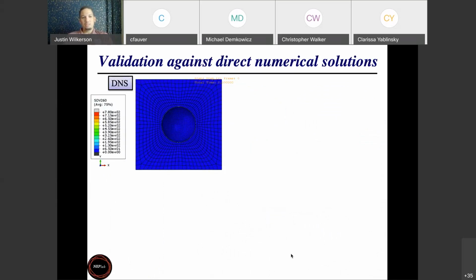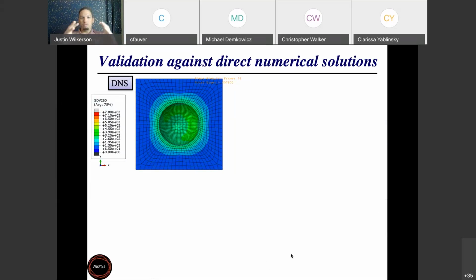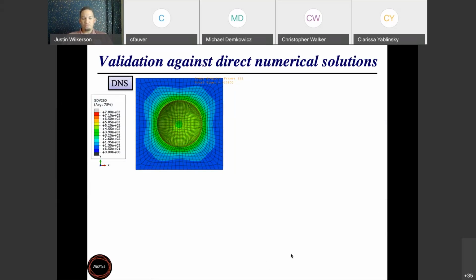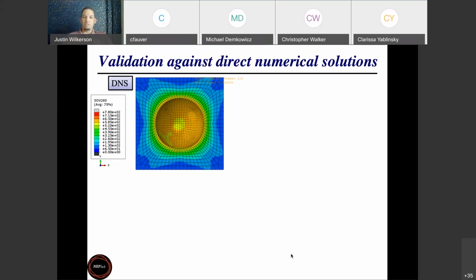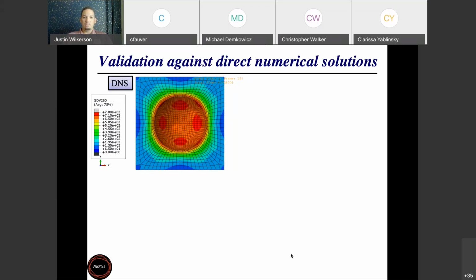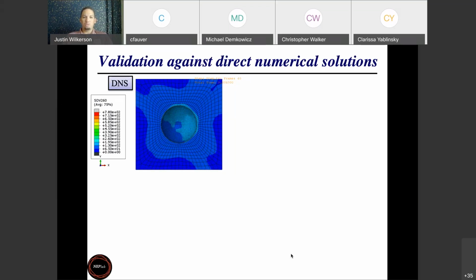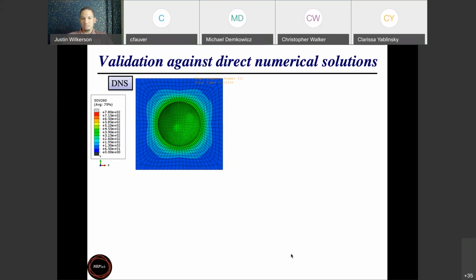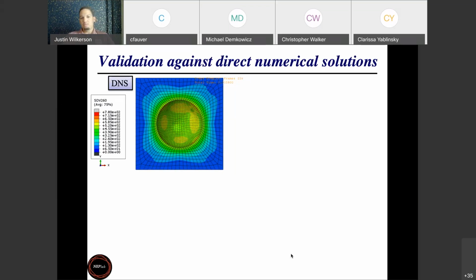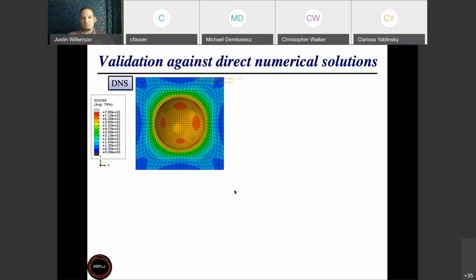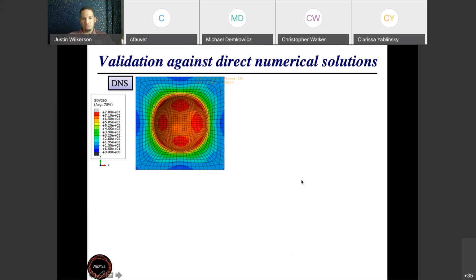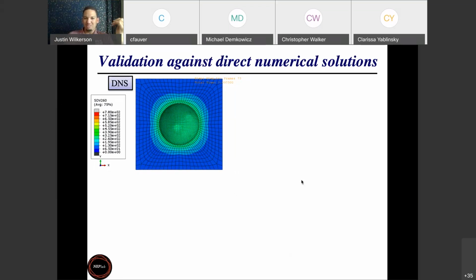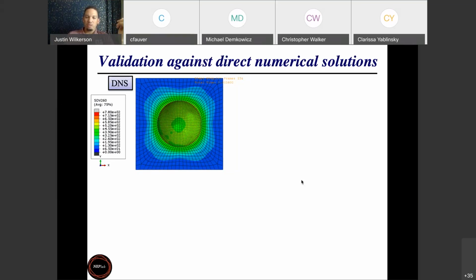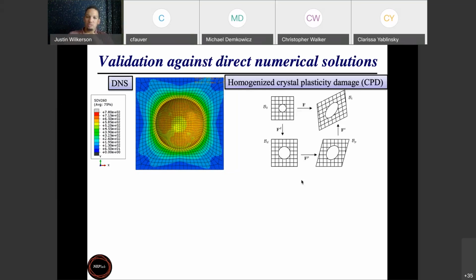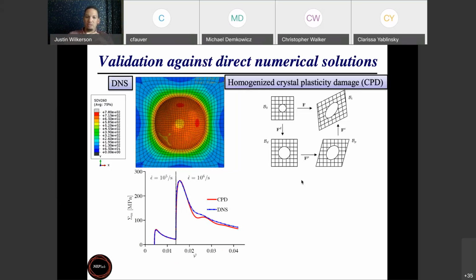and then we can compare with some direct numerical simulations that resolve voids explicitly. So here on the left, I have a DNS calculation where we're growing a void in a single crystal of copper. We apply a very high strain rate on the outer boundaries, and this void will grow. The contour plots are showing you dislocation density. So you can see that it's fairly spherically symmetric. There's a little bit of non-spherical symmetry due to the anisotropic crystal, but it's not a ton. And then we have this homogenized framework that we've discussed earlier, and then we can compare the two.